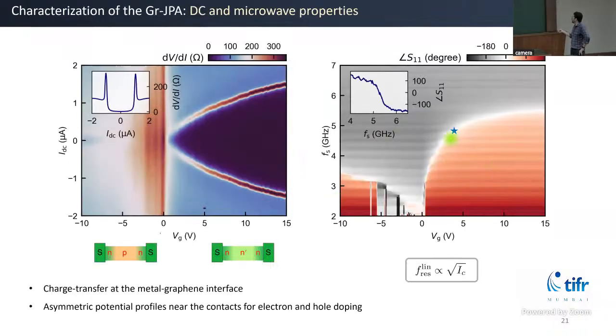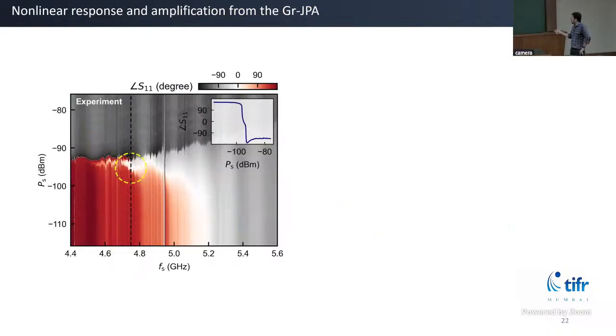So next, what we do, we park the gate voltage at a fixed value and now explore the nonlinear response. So here I'm showing you again the phase response, now as a function of frequency and power. As I said, when you increase the power for this nonlinear system, not only does the amplitude response increase, the resonance frequency starts to bend toward the left side. So this is what you are seeing here.